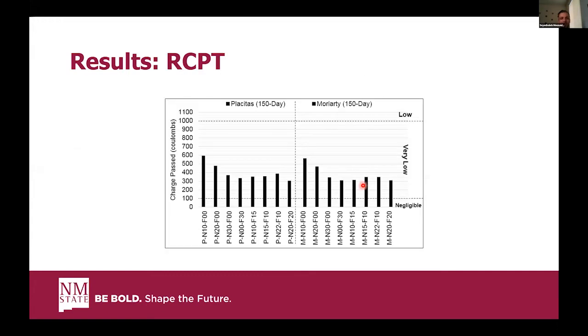Based on the RCPT, we found that all mixtures' chloride ion permeability was in the category very low based on ASTM C1202. And with increasing the natural pozzolan here, you can see that the permeability decreased and it came closer to the negligible area for both types of aggregates. But the more important point here is that the permeability of the mixture with 30% fly ash was really close to the mixture with 30% natural pozzolan. So again, you can suggest that this pumicite is a good alternative to fly ash in terms of RCPT, because the permeability of the mixtures with the same percentage of the SCM was really close to each other.